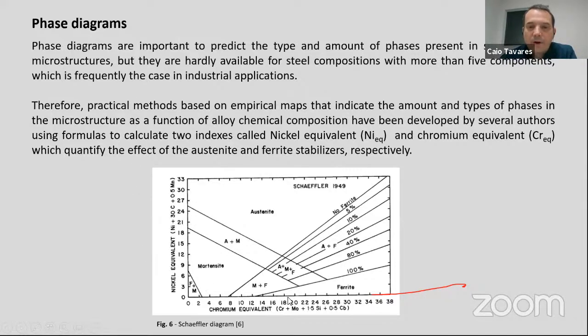This is an example of an empirical method, where we have the chromium equivalent and nickel equivalent. So what the author did was take other elements like carbon and manganese and convert them to a nickel equivalent. Here I have molybdenum, silicon, columbium, niobium, which are converted into chromium equivalent. So in this way, we have a 2D phase diagram that makes it easier to predict the microstructure.